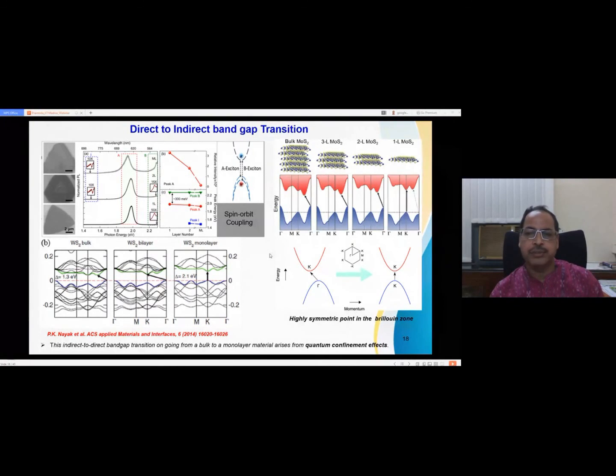So this material shows a direct band gap in the monolayer, and when it is bilayer or trilayer, there is a transition to indirect band gap. So this is the beauty of this material. Here you can see the theoretical calculation of one layer MoS2, the band gap is 1.85. When it is bulk, you can see around 1.35. Here is also a theoretical calculation of tungsten disulfide. Its band gap is close to 2 eV in the monolayer limit at the K point, but when it is bulk, it is an indirect band gap semiconductor. There is a transition from the gamma point to the K point.